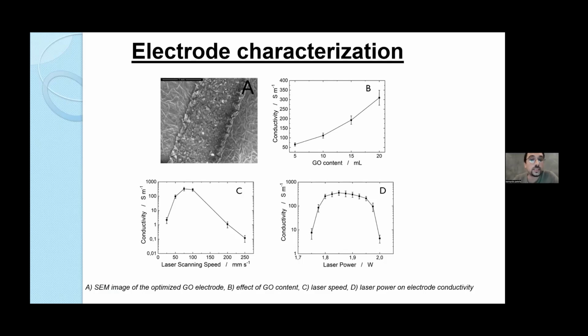So then we have tried to understand how much graphene oxide we had to put on top of the paper. So we have studied the effect of this parameter on the electrode conductivity. And as it's possible to see, the higher the amount of filtered graphene oxide, the higher the conductivity of the electrode. But by filtering 20 ml of solution, we have found the best conductivity, and we didn't exploit a higher amount of graphene oxide simply because the filtration process then takes too long, more than 5 hours. So we have stopped at this amount.